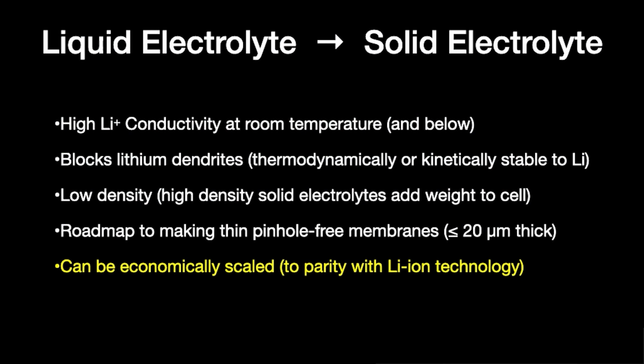So as we move to the solid state, that necessarily means we're replacing liquid electrolyte with solid electrolyte. And that requires a number of key metrics. We need high lithium-ion conductivity at room temperature and hopefully below. This solid electrolyte should block lithium dendrites and be either thermodynamically or kinetically stable to lithium. And you want a low-density material because otherwise this passive component will be adding a lot of weight to the cell, which you certainly do not want to do. There needs to be a roadmap for getting to very thin materials, hopefully below 20 microns, and they need to be pinhole-free so lithium does not short the cells. And obviously, ultimately, it needs to reach parity economically with lithium-ion technology. That's a big challenge. So let's look at some of the possible paths here.